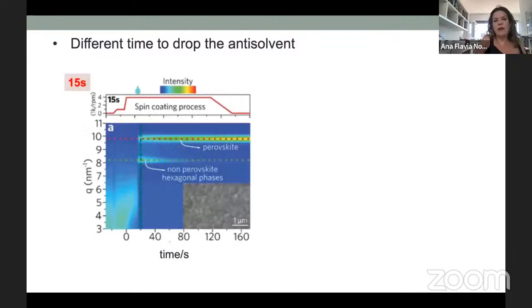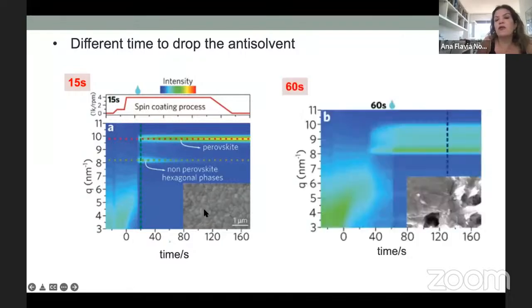And then we decided to change the time to drop the antisolvent, because this was done totally in our lab. If you use this antisolvent method, this is done manually, okay? So this is nice. When you drop the antisolvent 15 seconds after the spin coating process, at the end you have a very nice morphology of the film. But look at what happens if you take too much time to drop your antisolvent.